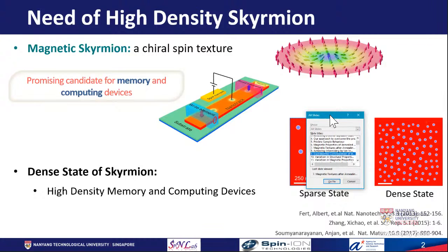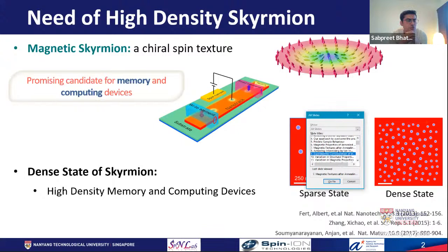Because it's actually quite a challenge to get such a material, because DMI and effective anisotropy are both interfacial phenomena. If you have a smoother interface which promotes both DMI and effective anisotropy, both values will be high. In most studies the effective anisotropy is so strong that it dominates the domain wall energy. So even if we start with such a sample, the domain wall energy is always a point of issue, where we have to compensate density to a certain value. That's why I showed the studies where they made the interfaces smoother: they were able to limit the skyrmion density to around 20 skyrmions per square micrometer, whereas here we were able to achieve around 50 skyrmions per square micrometer.